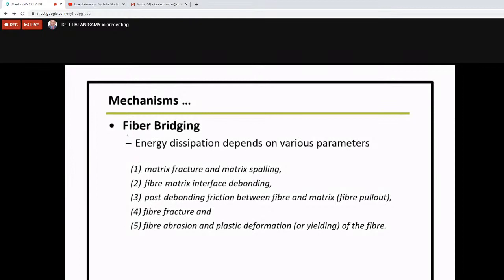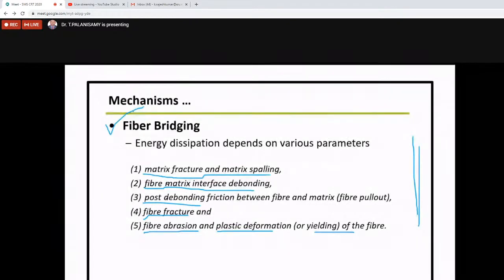The next bridging is fiber bridging. The energy dissipation depends upon various parameters. One is matrix fracture and matrix spalling. Another is fiber matrix interface debonding. Another is post debonding friction between fiber and matrix, fiber pullout, fiber fracture and fiber abrasion, and plastic deformation or yielding of the fiber. So the first is the aggregate bridging mechanism, and another is the fiber bridging mechanism. After that, we combine these two and see how the materials behave.